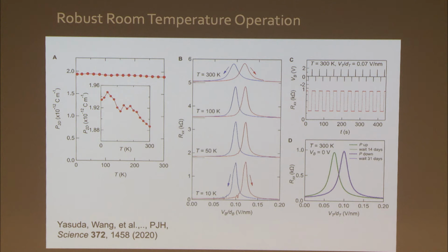Okay? These ferroelectrics work at room temperature. It's about the only thing I've done in my lab which works at room temperature. I'm very proud of it. So it's very robust. It's stable. You can cycle these thousands and thousands of times. Okay? You can wait for as long as you want. The ferroelectric state remains. It actually is extremely fast also. I'm not showing the data, but this thing switches faster than a nanosecond, which is very fast by conventional ferroelectric standards. Okay? It's about as good or better than state-of-the-art technologies. So who knows? Maybe this thing one day could be useful for something, and that would be great.